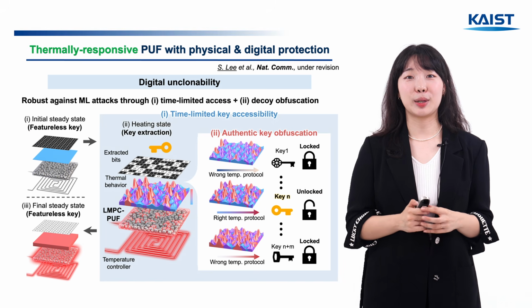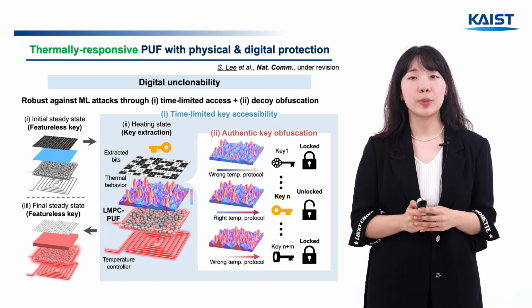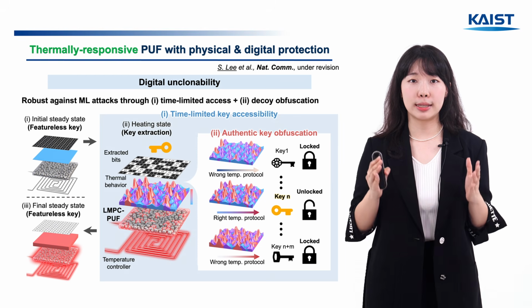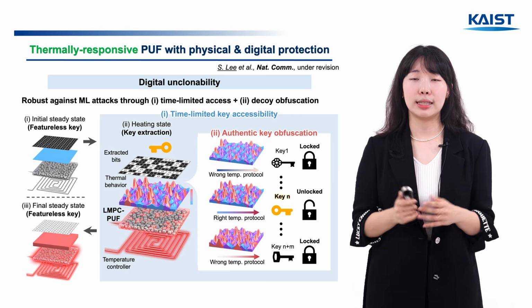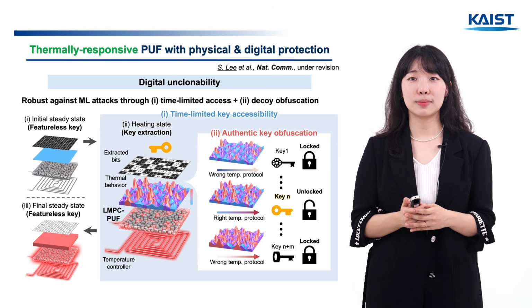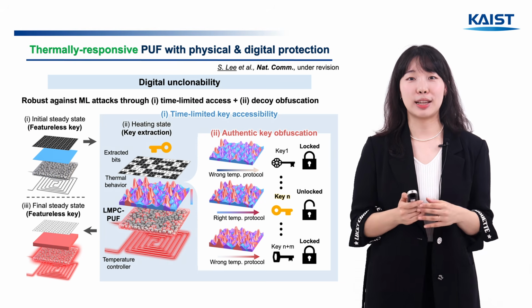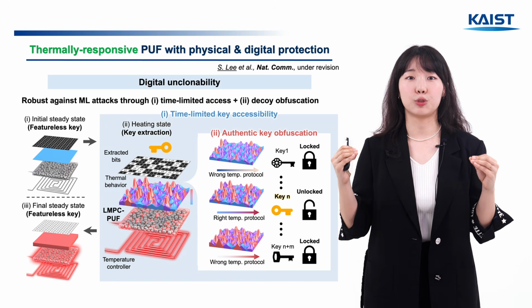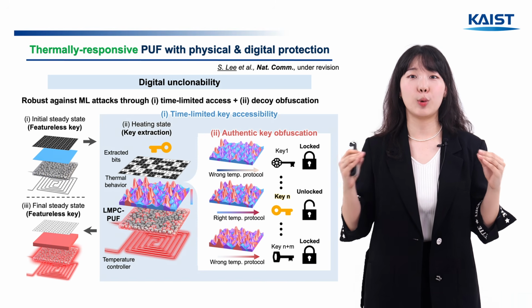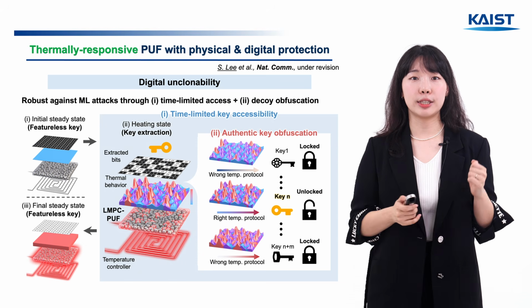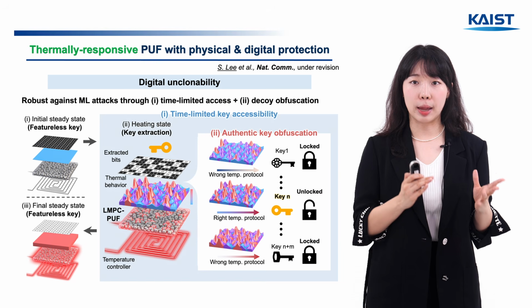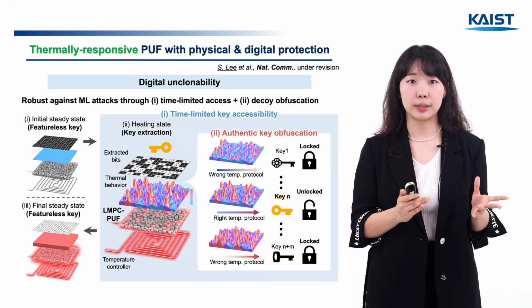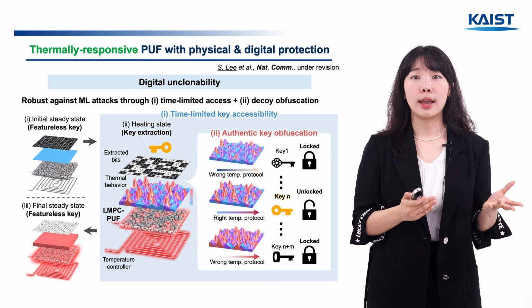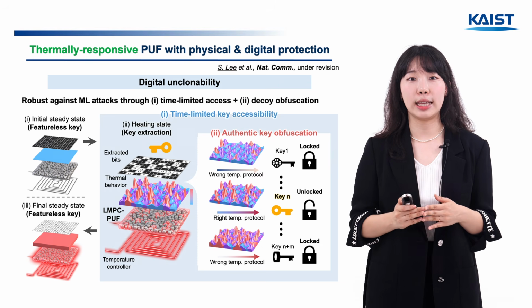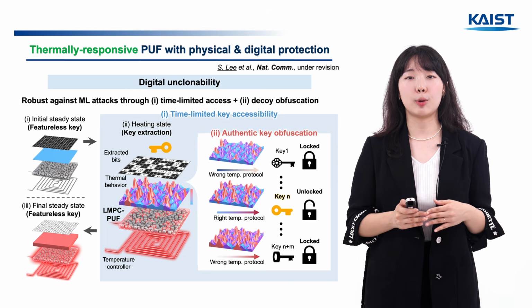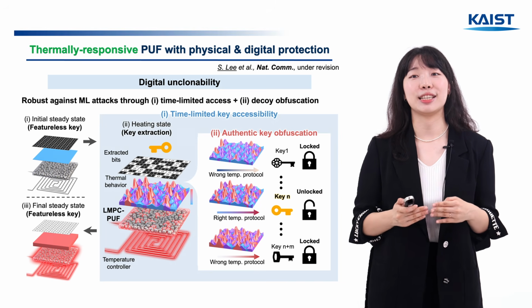Next is how digital cloning is prevented. In my PUF, the CRPs are only accessible during a specific window of time, and the real key is disguised among the fake CRPs. Here's how it works. When you set a start temperature and an end temperature of the controller beneath the PUF, you create a window in which the temperature changes. At the start temperature, all the particles are at the same temperature, so no thermal pattern appears, and no meaningful key comes out. While the temperature is rising, each particle heats up at a different rate, so a unique thermal pattern, which is the key, is generated.